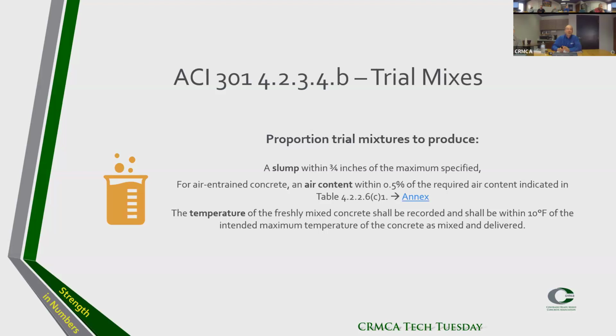So here we already see an issue, because many of the mix designs are done in winter in a nicely cooled lab, 60 to 70 F. So you get really good strength. I've seen that several times. And then we have an issue in the heat of the summer. In July, temperature is in the 90s. So you are really above the 10 degrees that it was done for the test mixture, and we're going to see lower strength. So that's something to consider when we do test mixtures in the lab.